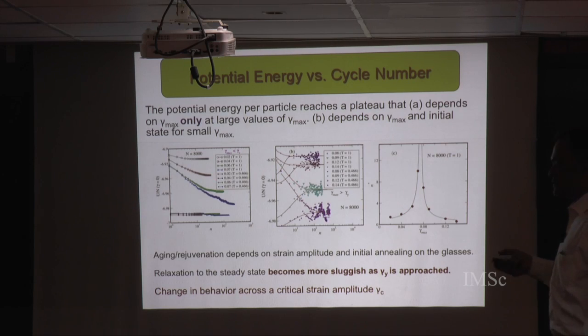So what that means we'll talk about as we go along, but one interesting feature is, if one looks at how long it takes for the system to reach an asymptotic state, that number of cycles shows non-monotonic behavior. For these set of states, the number of cycles needed is an increasing function of strain, whereas for these set of states, it's a decreasing function of the strain amplitude. There seems to be some critical value of the strain amplitude across which the behavior changes, at which the number of cycles needed to reach the steady state is diverging.